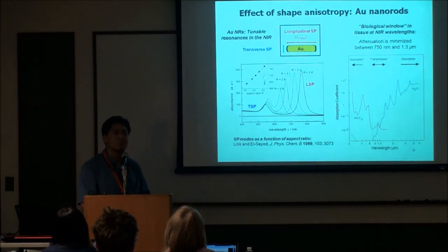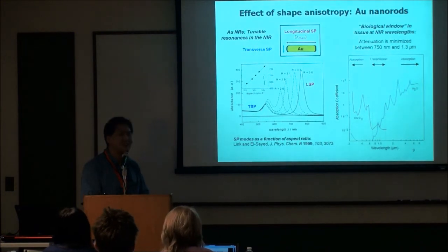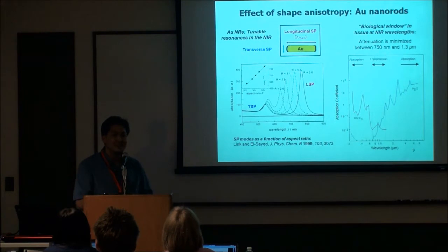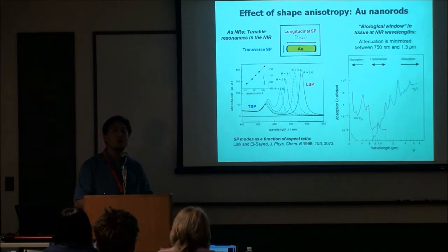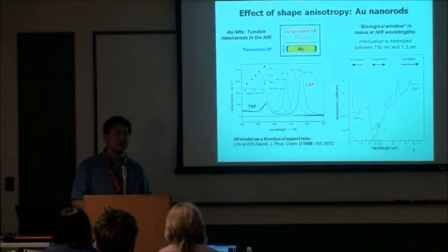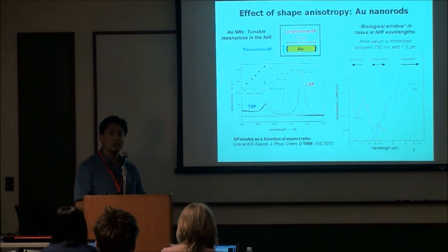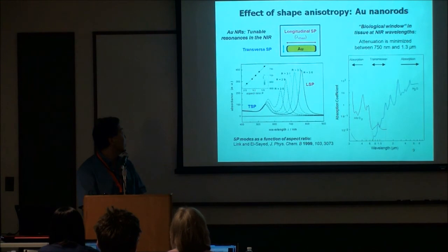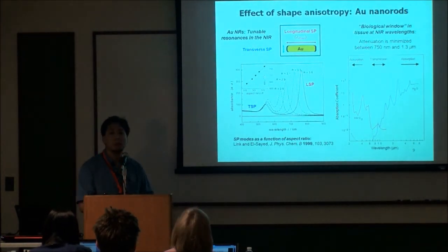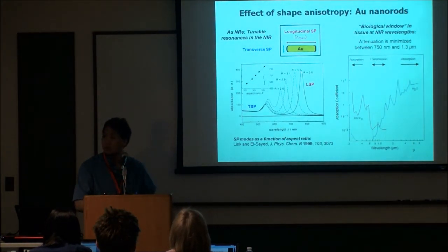One of the persons responsible for developing practical methods for synthesizing gold nanorods, the godmother of gold nanorods, is Catherine Murphy, who's at the University of Illinois. She and Mostafa El-Sayed at Georgia Tech really deserve most of the credit for defining how one can construct and tune gold nanorods to give you the wavelength of interest. Notice that as you change the aspect ratio, you have a quasi-linear relationship between the wavelength and the aspect ratio. It's empirical, but still very useful for predicting what we get out.